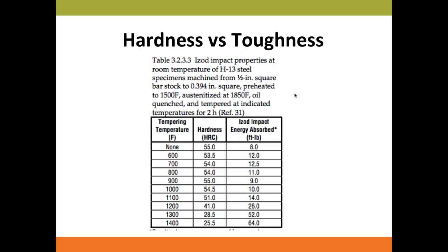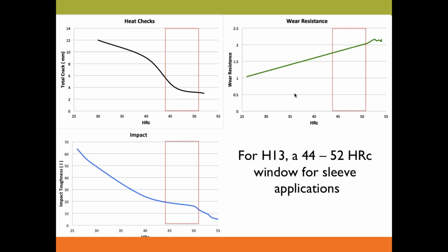And on top of that, when the Rockwell is different, the hardness is different, the impact will be different as well. So for the heat checking, it's positive in proportion. When you have a higher Rockwell, the heat check resistance is higher. But for the toughness, when you have a higher Rockwell, the toughness is lower. And I put these two into a graph and also put the resistance index into it.